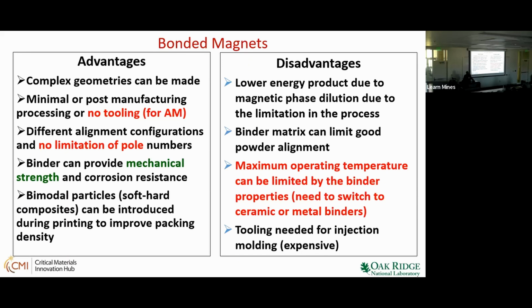Brayton talked about the sintered magnet being strong, and it's still strong. But you can add strengthening agents into this bonded magnet. Or another thing you can do is bimodal particles, so you can vary the particle size and improve the packing density. The disadvantage is you are diluting with a polymer, and you are losing the energy product by the square of the fraction. So you are losing very significantly. That's a challenge when you use a bonded magnet.